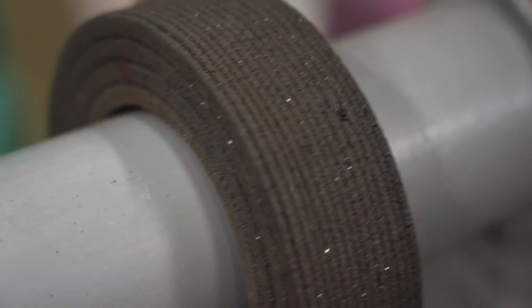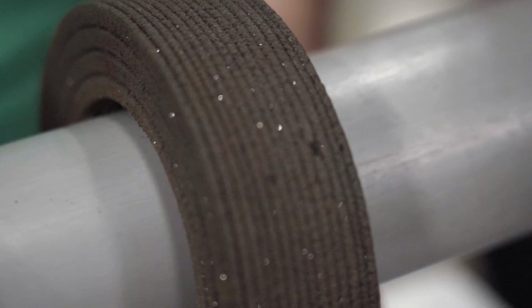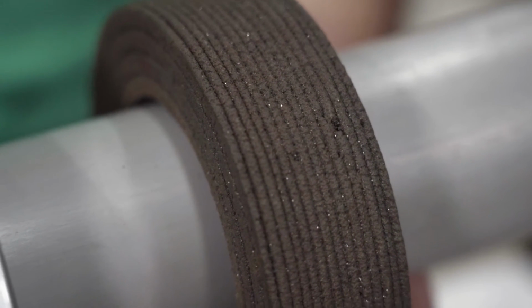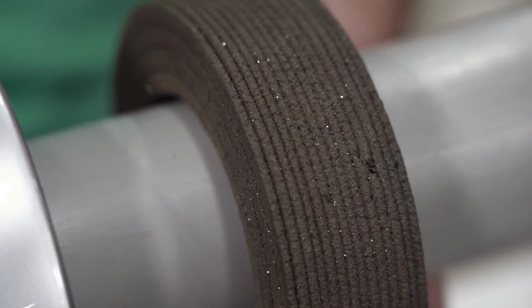Because the higher the loading, the performance goes up exponentially. The magnetic performance, especially the energy product, is directly proportional to the square of the volume of magnet material present in a composite. So let's say 70 volume percent, 0.7 squared, you get only 50% of your starting magnetic performance. So if you want to achieve full density, you want to increase the loading.